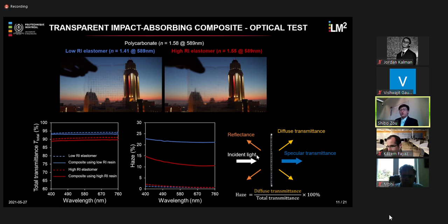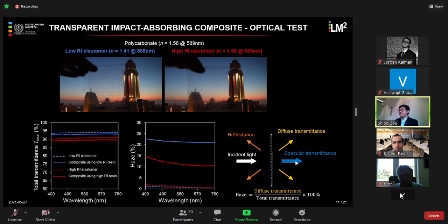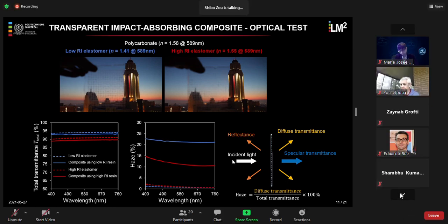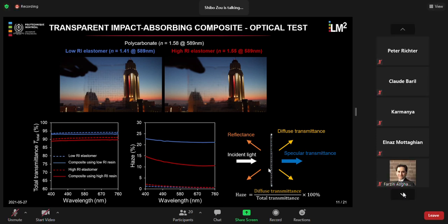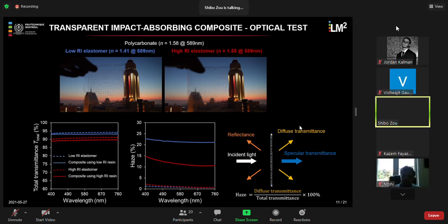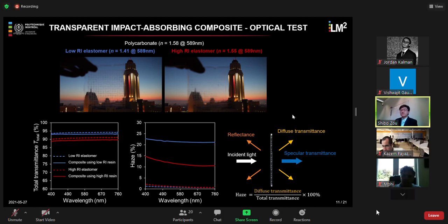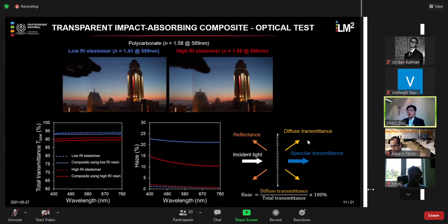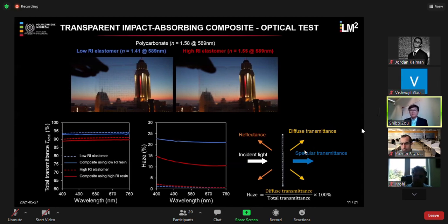So we also want to know how the difference in the refractive index between the matrix material and the fiber will influence the scattering properties of the material. As you can see here, this is a schematic of the optical test that we did. As the incident light transmits through the material, the total transmittance actually includes two components. One is the specular component, and the other one is the diffuse component. So we can define haze as the ratio between the diffuse component over the total transmittance. This gives us a better idea of how much light was scattered by the composite film.